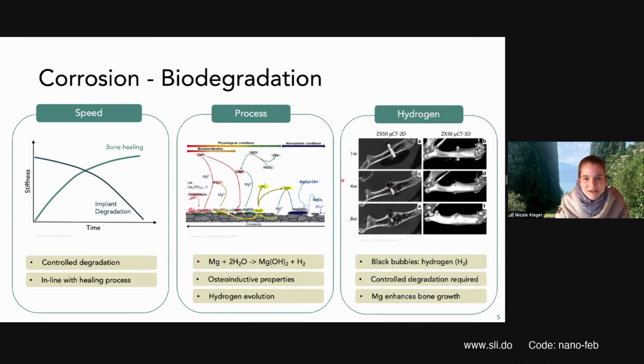So what you see here are micro CT images of a degrading magnesium pin in a bone. And all these black areas around the pin, this is actually hydrogen gas that is formed during the degradation of magnesium. Now, as long as this degradation is controlled and slow, the body can handle this hydrogen gas and it will dissolve and be transported away from the degradation area. Now, what you also see is that the bone is actually growing in the areas around the pin. And this is, as I said before, because magnesium enhances bone growth.